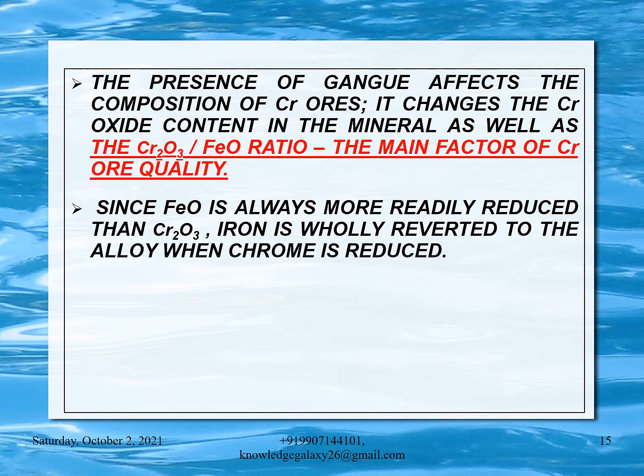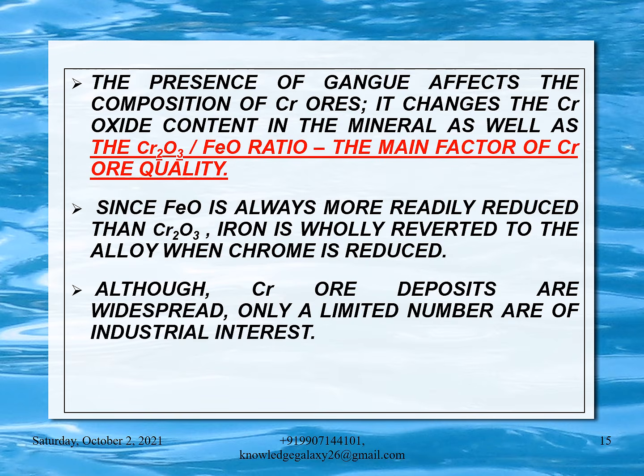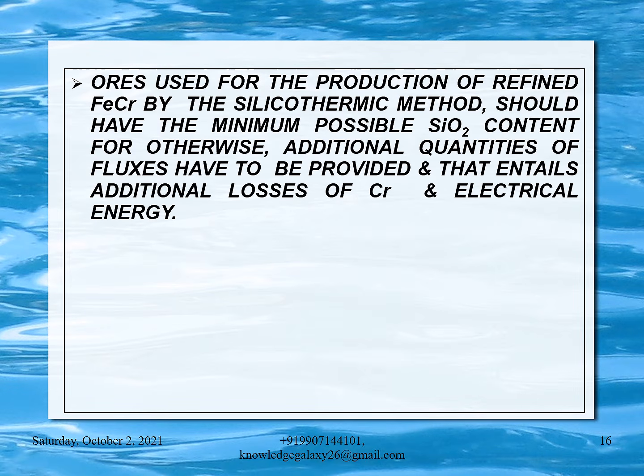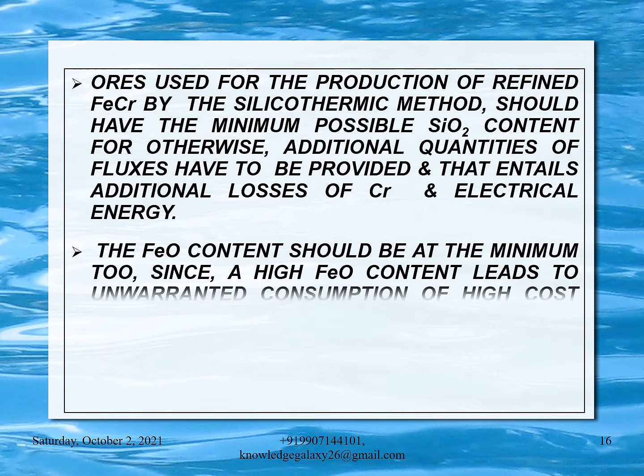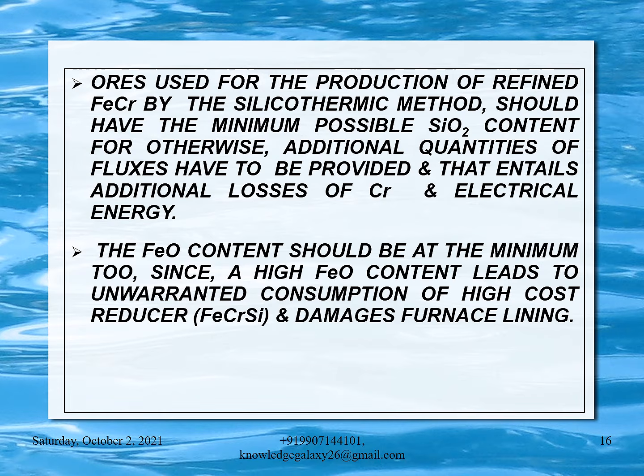Since FeO is always more readily reduced than Cr2O3, iron is wholly reverted to the alloy when chrome is reduced. Although chromium ore deposits are widespread, only a limited number are of industrial interest. Ores used for the production of refined ferrochrome by the silicothermic method should have the minimum possible SiO2 content, for otherwise additional quantities of fluxes have to be provided, and that entails additional losses of chromium and electrical energy. The FeO content should be at the minimum too, since a high FeO content leads to unwarranted consumption of high cost reducer ferrochrome silicon and damages furnace lining.